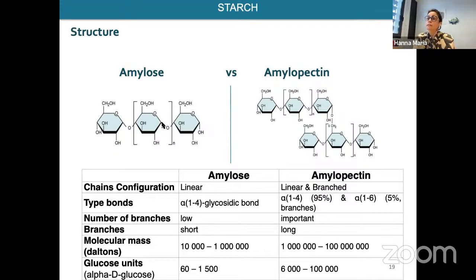So as you can see here, 1, 2, 3, 4. So we have 1,4 glycosidic bonds. And in the case of the amylopectin, most of the linkages are 1,4 again, 1, 2, 3, 4, but we also have around 5% that is alpha 1,6. You can see here carbon 6 is linked to carbon 1 of the other chain, and this makes the branch of this polymer.